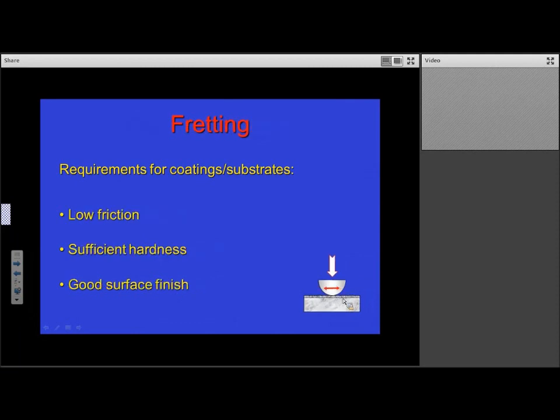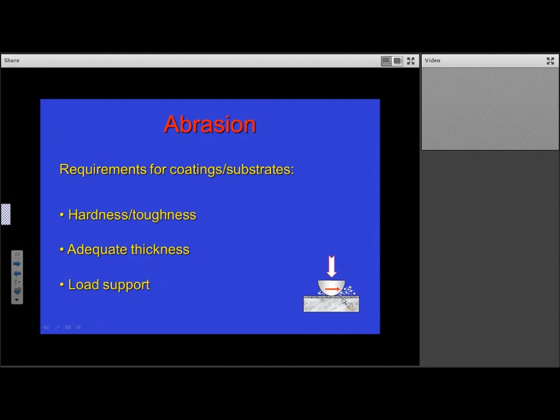If you think about fretting, that's a very low amplitude fatigue type situation. You often need low friction, again sufficient hardness, but there's still a lot of discussion over the relative importance of hardness and ductility in fretting contacts, and you need good surface finish. In abrasion, that's probably the mechanism where you really do need hardness. Many studies have shown that typically to resist abrasion by a hard abrasive particle or a hard counterface, your surface should be at least 30% higher in hardness than the abradant. So for sure we need hardness, but we also need toughness. We need adequate thickness of the coating so that any abradant doesn't penetrate through the coating. And then you need load support underneath the coating, again, to prevent that abradant penetration through the coating.